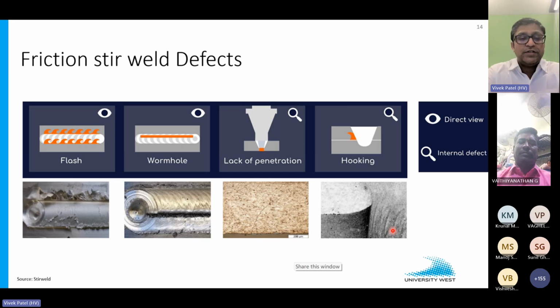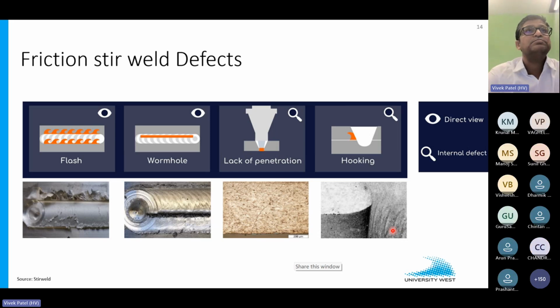Then, yes, every manufacturing process has defects. But it's all about how you can tackle, minimize, and eliminate those defects. So in friction stir welding, the defect that you can see with the naked eye is flash on the surface. You can see in the picture one example of flashes. So you see a lot of flashes on the surface. This is a defect, but it can be tackled by post-welding treatment. You can do deburring or machining, but that is not the ideal case. This defect is a result of a higher heat input condition. So we call this a hot welding condition.